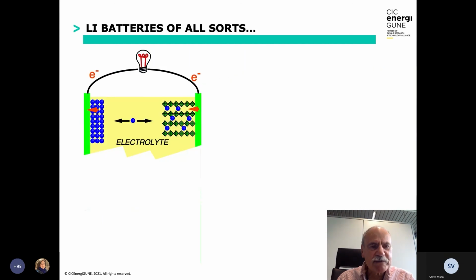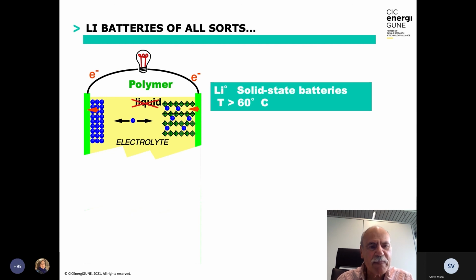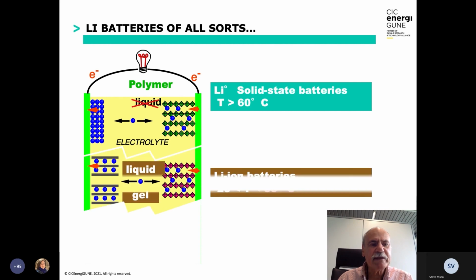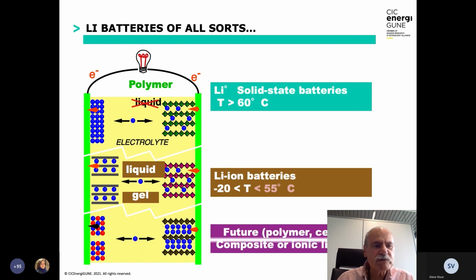If we think of batteries according to chronology, batteries started to be lithium polymer batteries with an intercalation cathode and a metallic lithium anode. They are solid-state batteries working because the electrolyte needs to be warmed up to become conductive enough, above 60 degrees. Then came the lithium-ion batteries after 1991, where the liquid electrolyte is used between two intercalation electrodes, graphite and something like NMC, and the temperature of operation is between minus 20 and 55 degrees, where you start to have safety problems. And what is the future of batteries?